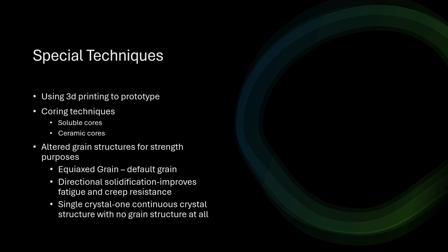The second type is directionally solidified. In this technique, casting is cooled in a controlled way so that grains grow in a single direction, usually along the axis of highest stress. This removes transverse grain boundaries, improving fatigue and creep resistance in high temperature applications.